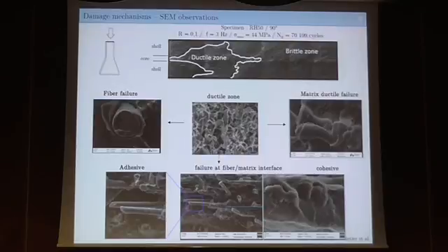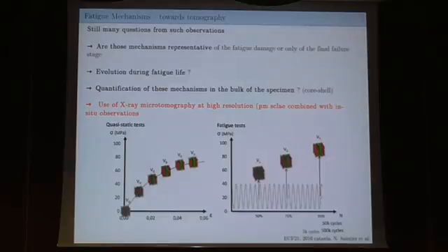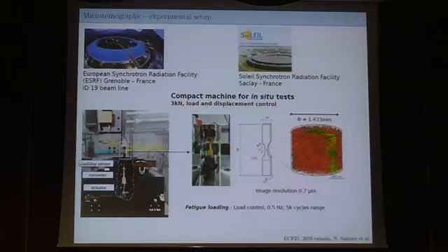The only way to have this information is to go to synchrotron and to try to observe the evolution of damage as a function of the stress level, if you look at a uniaxial tensile test, or as a fatigue level, and you do some cyclic loading, and you do interrupted tests, and you look at the microstructure. The key challenge here is to look at the very same microstructure. So our focus was really to watch the same specimen during different stages, and the same microstructure. So we did X-ray microtomography at Synchrotron and Soleil facilities.